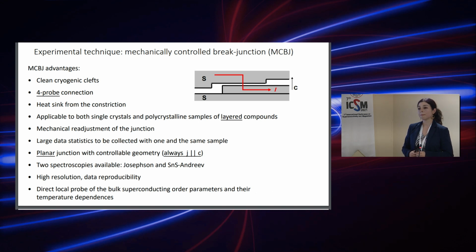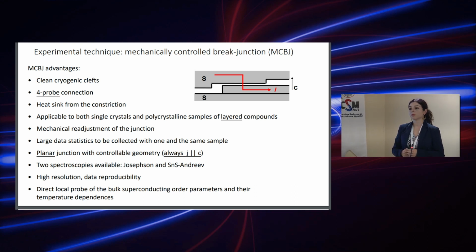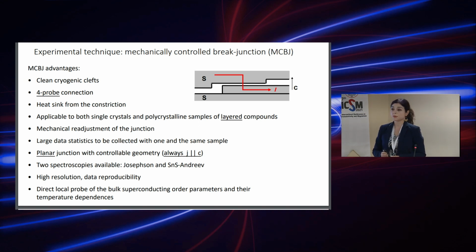So I don't understand. You have something there or not? No, it's just vacuum. Just a crack, broken chemical bonds. And what is the dependence of your signal on the thickness of this crack, let's say? We could control the resistance of the junction. Typical resistances are from 1 ohm to 100 ohm. So what do you prefer, a thin N or a large N, or what is it? There is some optimum value, I don't know. There is no hole between two superconducting banks, they just slide onto each other. So this is just broken chemical connections.